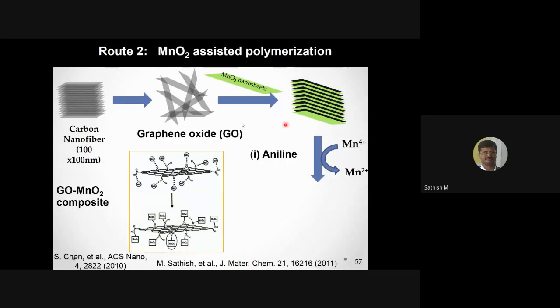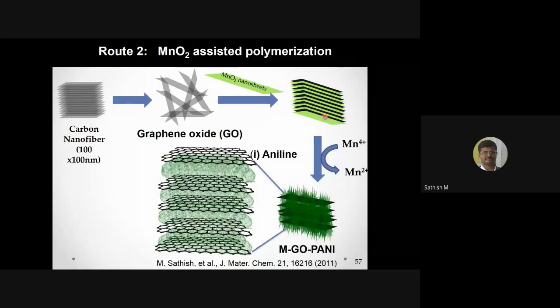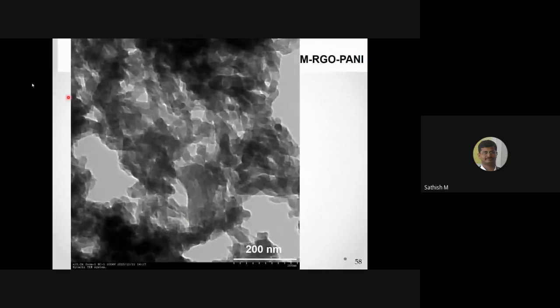So there is an oxidative polymerization process. That means the manganese 4+ in this manganese oxide will reduce to manganese 2+ and come into the solution. Then the electron goes to the aniline, and it gets oxidized and initiates the polymerization. This process is called oxidative polymerization. In such a case, only when the manganese oxide comes out does the aniline get polymerized inside, in between the two sheets. So you can end up with this kind of controlled polymerization of aniline. So you could have graphene polyaniline. This is the graphene polyaniline mixture we have got.